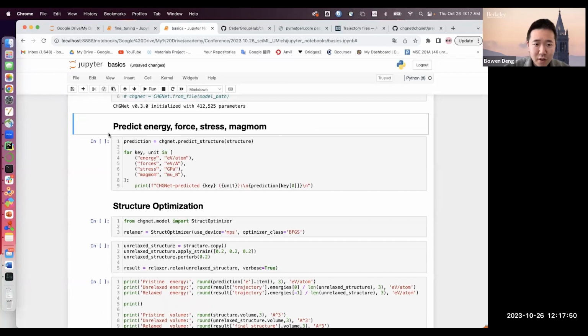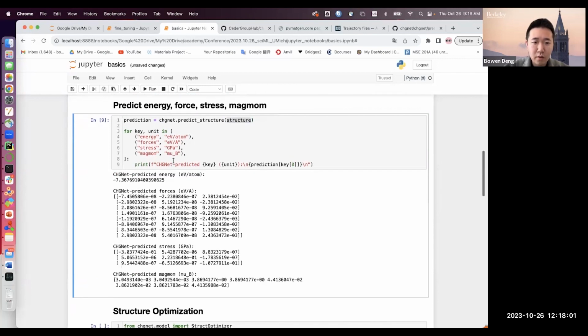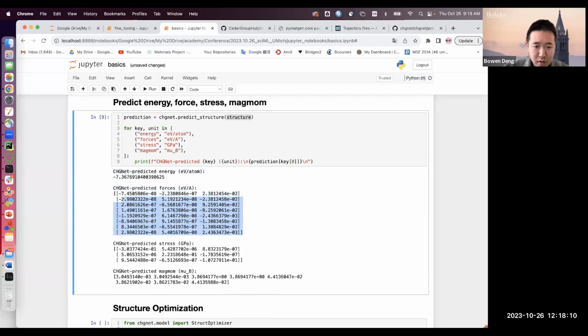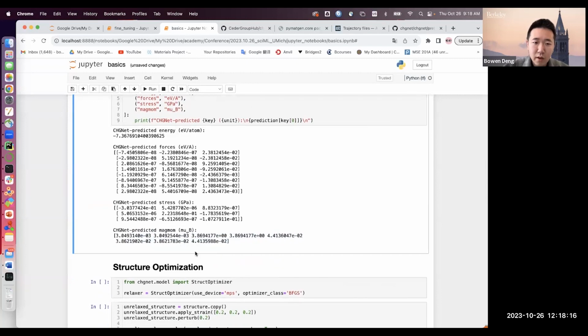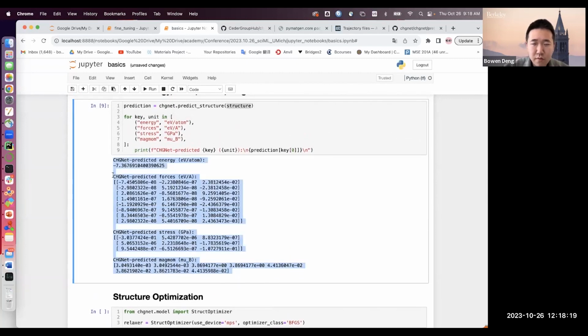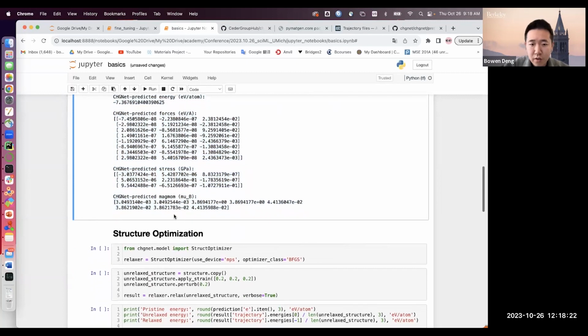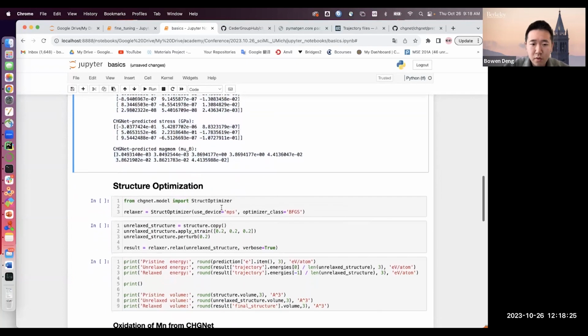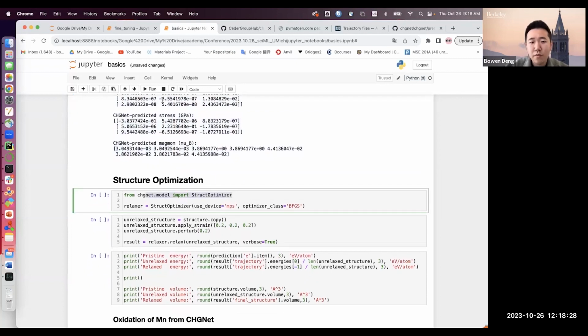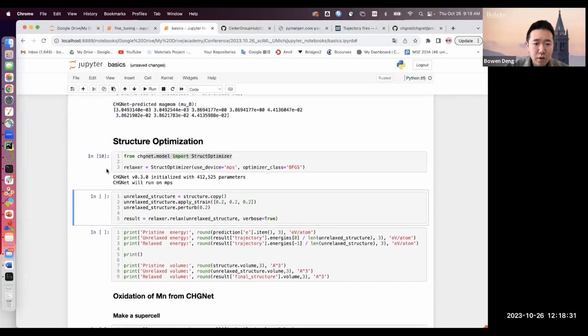To predict the energy and all the properties is just one line of code. Prediction equals CHGNet.predict_structure, and you give the structure into this function. And here you can see within 1 second, it gives you the system energy in eV per atom, the forces on each atom, the stress, and also the predicted magmoms. These are the essential components for machine learning potentials. We can inject this information into, for example, a structure optimizer, so that we can use this force information to relax a structure.